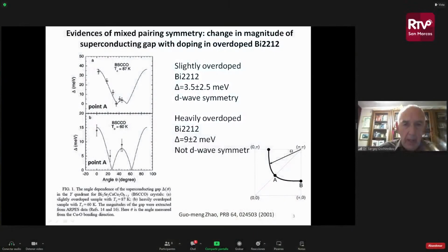You can see here a maximum, not a minimum. For a D-wave gap, we should have a zero gap. But for this material, strongly overdoped cuprate, we see the maximum, not minimum. So it is the first example of the S-wave gap, extended S-wave gap. It was published 20 years ago. This is the reference at the bottom of the picture.